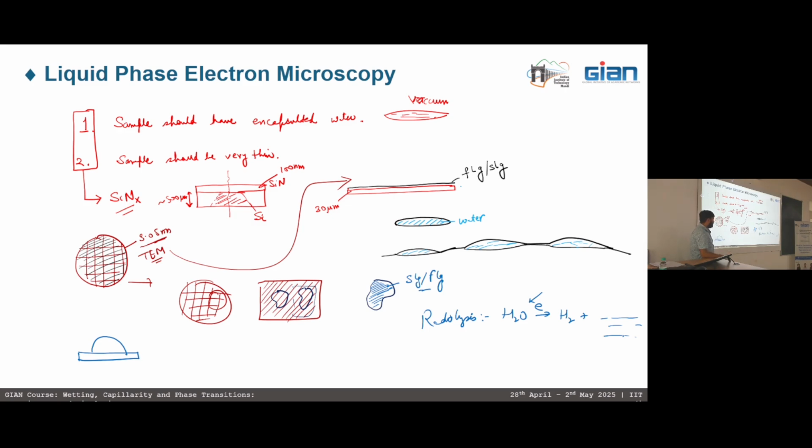The third very important step is that since it is a wet method, you have to dip this inside APS, which is in liquid form, and in liquid, surface tension is the main culprit. This surface tension can damage the graphene films as well. So you have to put it in very gently. A lot of control over the hand is required, so that these grids don't fail, and the graphene doesn't get cracked or shattered in this process.